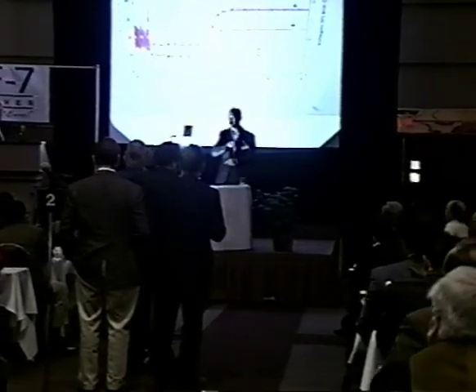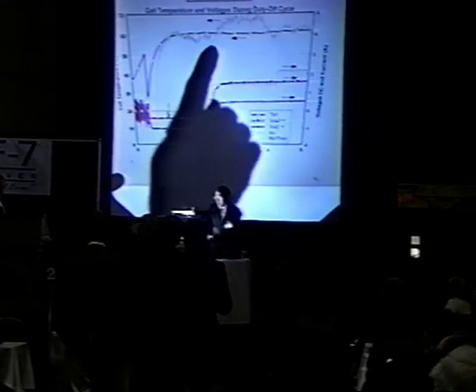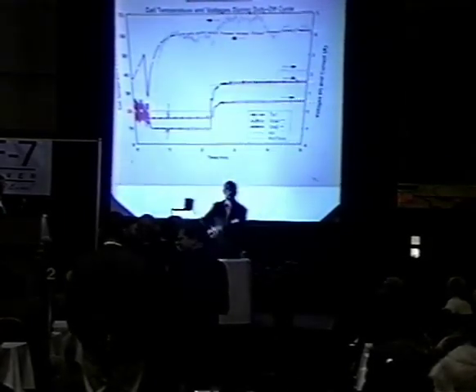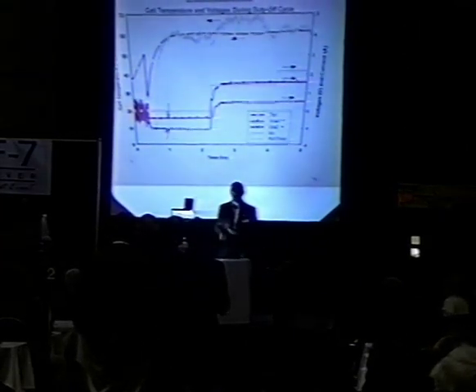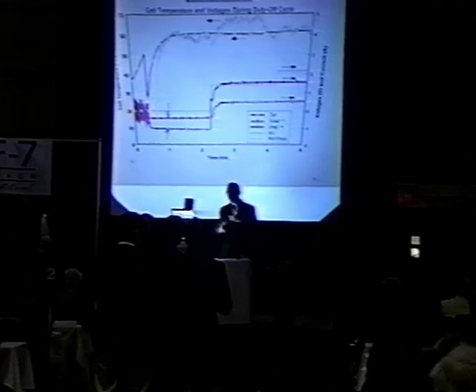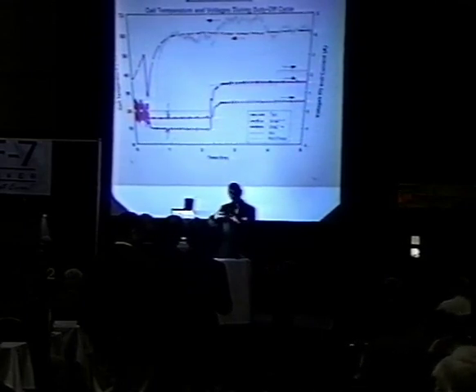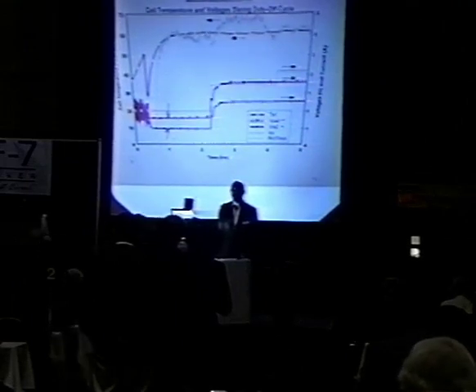I understand your concern. In fact, there were things that surprised me as well. For example, you mentioned the issue of the power changing very rapidly. Of course, you have to realize this is a long, 5-hour run. None of this stuff, like when I turn the current on and the power actually goes up some, is abrupt. It takes certainly 15 to 30 minutes before you start to see the change. It's not within seconds. And like the first one, when we first poured the solution in, it was probably 10 minutes or so after the solution was poured that it became obvious that this thing was actually producing heat. In other words, it takes quite a while to develop. I understand that. I was surprised as well. I thought that electrolysis was going to be a key feature in this. That's why I set it up to run as an electrolysis cell and to monitor that charging.